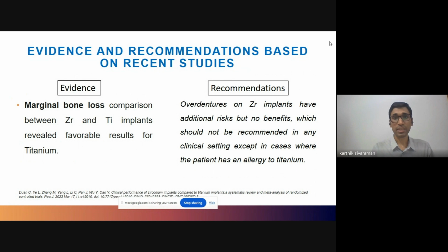Now, what could be the reason? The reason is that the occlusal forces which an implant under a single crown might be subjected to is much less compared to an implant which is subjected to forces under an overdenture. So the recommendation of the authors was that overdentures on zirconium implants have additional risk but no benefits, and they should not be recommended in any clinical setting. In any case, only where there is a documented titanium allergy should the clinician go ahead with a zirconium implant to receive an overdenture.